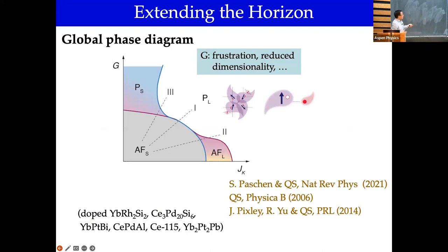And so I've emphasized this quantum critical point from the antiferromagnet side to the paramagnet side, going through a point. But one of the things that has come up in these different materials is that quantum fluctuations could be associated with a zero temperature point, but could also be associated with a zero temperature region. We were able to generalize the type of consideration which I've mentioned to you, with the loss of quasi-particles, which in the zero temperature limit should be confined to this point if you are doing this trajectory, to a broader perspective where it could be a phase. So in that sense, whether it's a quantum critical point or quantum critical phase is really, in the overall scheme of things, a small difference. The importance is that there's this type of Kondo-Landau quantum critical situation as the controlling physics.